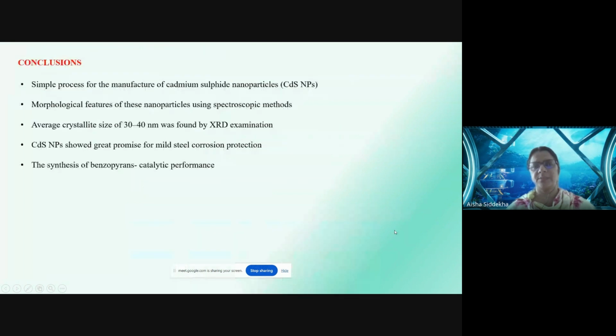After every cycle, we took the coupons out, dried them, and took their weight. Previously, the coupons were weighed, and after 1 or 2 days we took them out and weighed them again. From these weight loss studies, we found that these exhibit good corrosion inhibition under our lab conditions. So this was the other application.